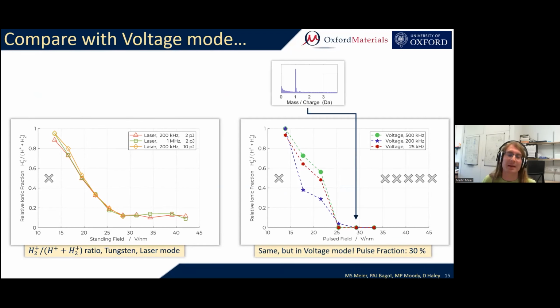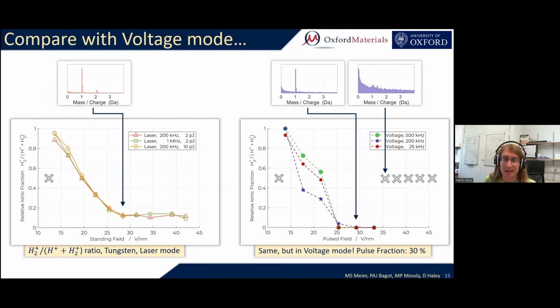Number 1, in voltage mode at high electric fields, the peak height ratio goes straight to 0. And that corresponds to a spectrum without a mass-to-charge 2 peak. And this is really something that so far we have not seen in any of the laser mode experiments. Secondly, in voltage mode, if the electric field is high enough, the spectrum becomes empty again. And it is also something that appears to be exclusive to the voltage mode experiments that we do here. Now, there are two possible ways in which we could interpret this empty spectrum in voltage mode.